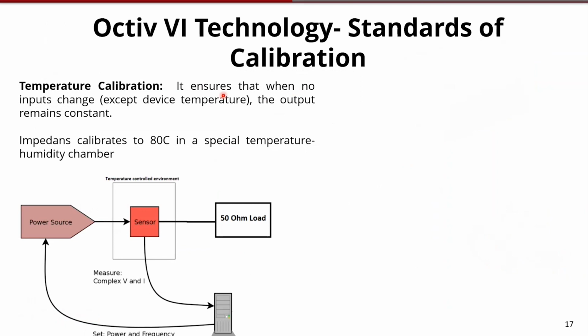so one thing is you have to calibrate by temperature. Because you don't want the sensor to give different measurements depending on the room temperature or the temperature of the cable if you're running high power or so on. It needs to be able to work at different temperatures. So we calibrate our sensors from room temperature to 80C in a special temperature humidity chamber. So all our sensors go through that. So that's something you need to do with a VI probe.